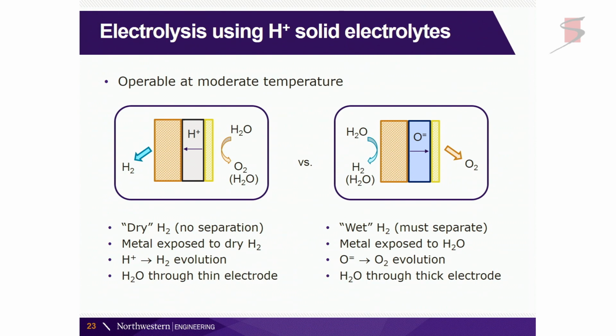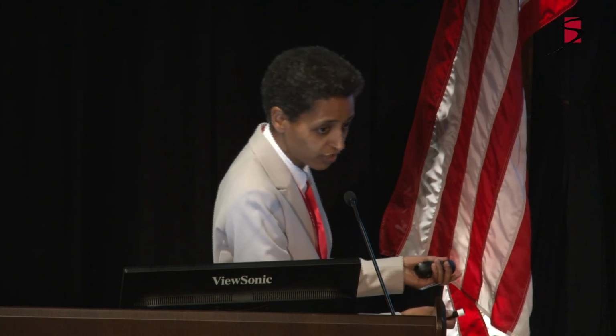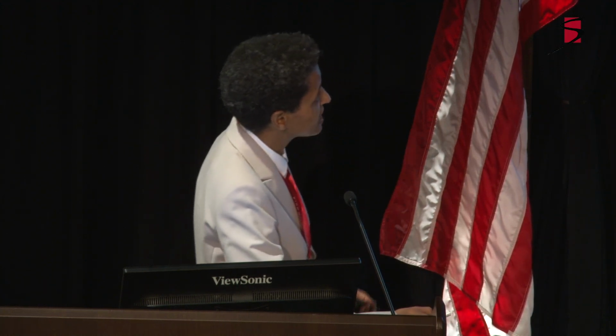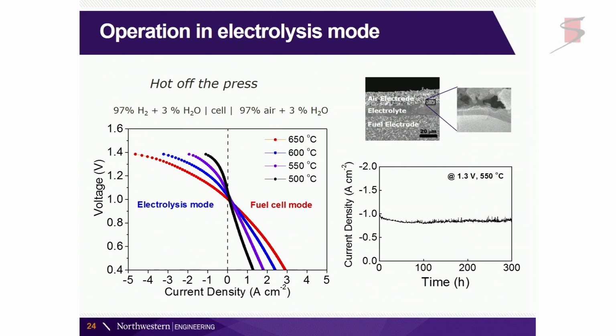So there are a lot of reasons why it is advantageous to use the proton conducting ceramic for the electrolysis. And so experimentally, it's very easy for us just to change the direction of our current. This is a straightforward experiment, and so we did that. We did one thing, which was put a high concentration of hydrogen here, and that's just historically what people do because you want to think about pressurizing the hydrogen to be able to put it into some sort of tank. And so we're operating in electrolysis mode and fuel cell mode, and we have good stability.